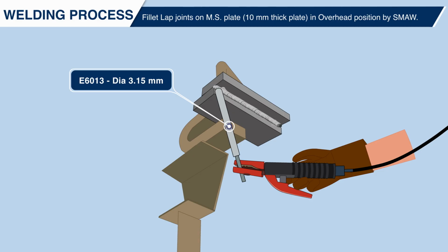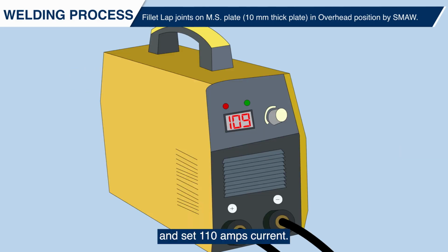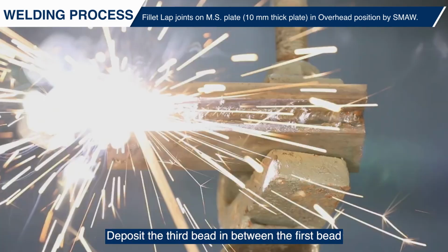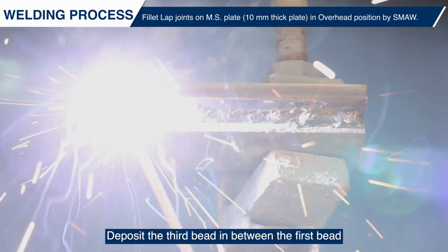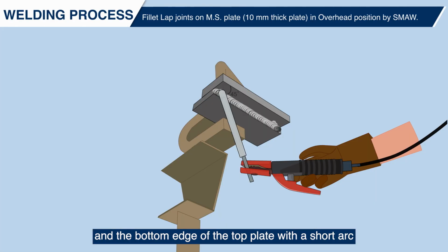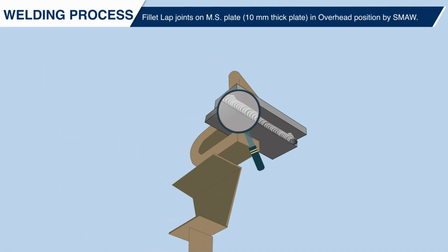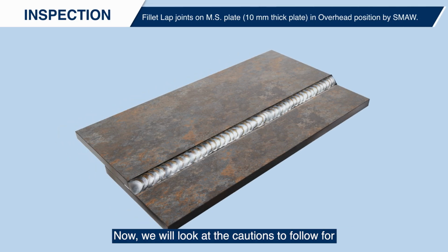Use 3.15 mm dia electrode and set 110 amps current. Deposit the third bead in between the first bead and the bottom edge of the top plate with a short arc and with an electrode angle of 45 degrees to the surface of the plate to avoid the edge melting off the top plate. Inspect the weld thoroughly.